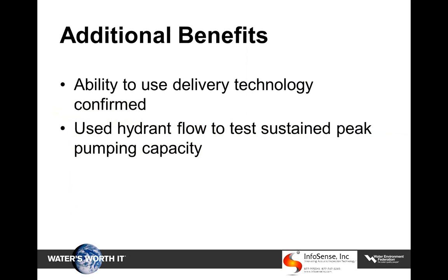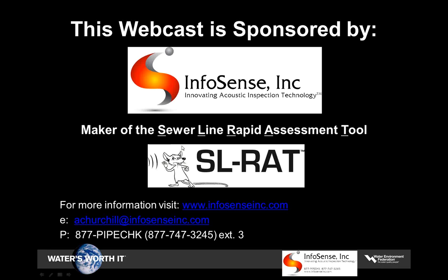Some of the additional benefits of the Smart Ball test is just the fact that we were able to deliver the technology. There were a number of thoughts among some of the folks in the agency about whether we'd be able to actually do that. We were able to confirm that. And we were also able to use the hydrant test to do some sustained peak pumping capacity tests at the pump station. Normally, if we wanted to do that, we would have to wait for it to rain hard and come into a CSO event, when most of the operators are fairly busy with other issues. We were able to, in a rather controlled state, use that hydrant flow to test the peak pumping capacity and establish some current pump curves. So that is pretty much it for the examples that I had.